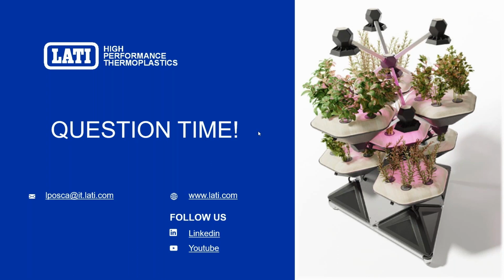Second question, did you test plastic in space and vacuum? Well, actually we did, with some partners in England and in Europe. And the results are the ones that I've just shown. Emissivity of this graphite-based thermally conductive plastic is more or less 0.85 or 0.89, something like that. And we measured the conductivity in air and in vacuum as well.